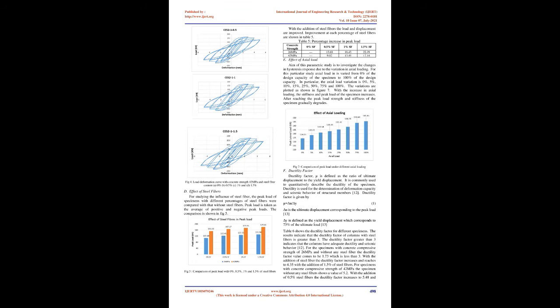Hysteresis curve is an important basis for studying the seismic performance. All the specimens as mentioned in Table 4 are analyzed with a constant axial load of 10% of the calculated capacity and lateral cyclic loading. For obtaining the hysteresis curve, reaction force is obtained from the bottom reference point and displacement is taken from the top face.